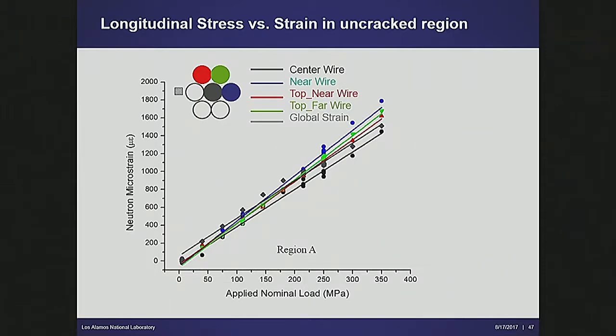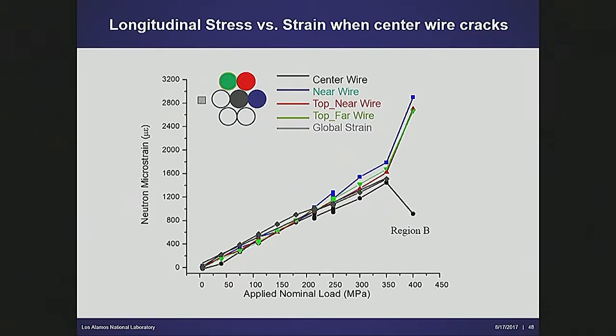What do you see? If there's no break, all of the wires, all of these 6 or 7 strands, you look at them individually, show much the same response. Here's the applied load, here's the measured elastic strain. Everything's hunky-dory. When you get a break in just one of them, the whole thing doesn't break at that point. But what happens is, this is the applied load. On the cable that broke, as you increase the load, the strain is now dropping. It doesn't go to 0, it's just unloading a little, while the surrounding cables take up more strain. So what you can see in this scenario is that the strand that broke is unloading, and the strands that didn't break are taking up more load.